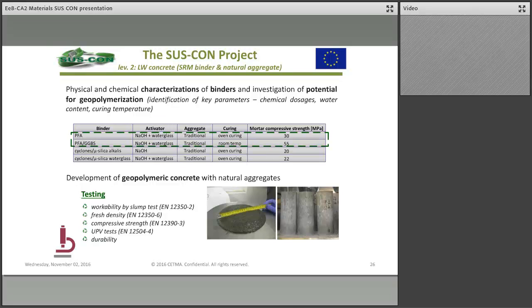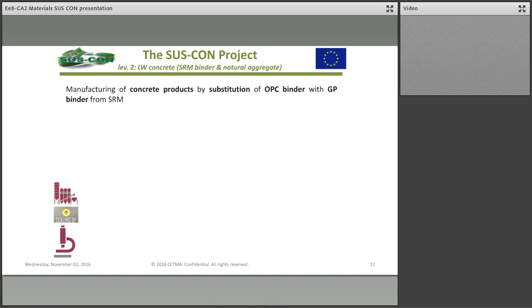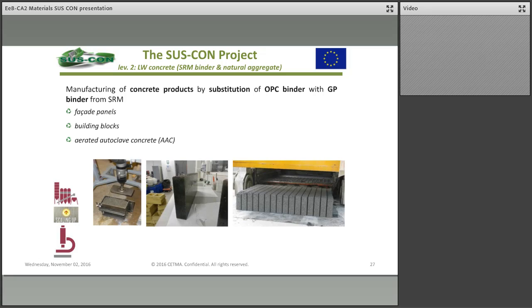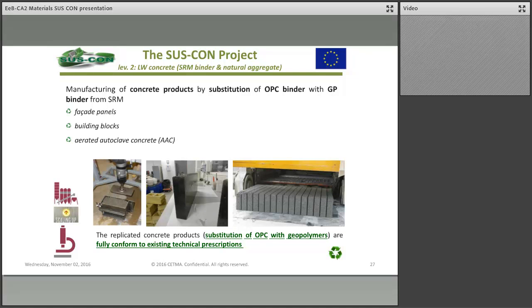And then we developed a geopolymeric concrete made with binder from secondary raw materials and natural aggregates, and tested them in terms of workability, fresh density, compressive strength, UPV test, and durability. Also in this case, we evaluated the chance to upscale such concrete from the lab scale to the industrial plant. So several concrete products were produced by substituting ordinary Portland cement binder with the SUS-CON binder from secondary raw material for applications like facade panels, building blocks, and aerated autoclaved concrete. And as a result, the replicated concrete products fully conformed to existing technical prescriptions.